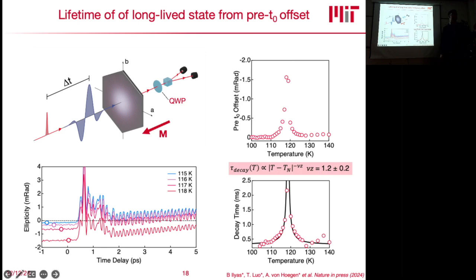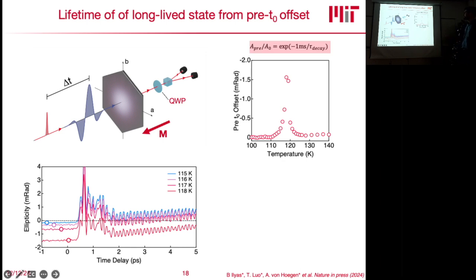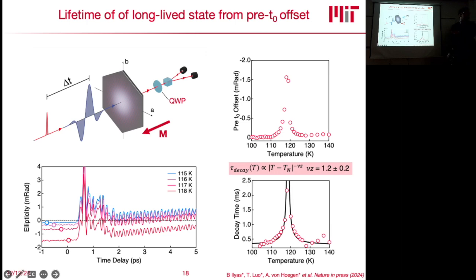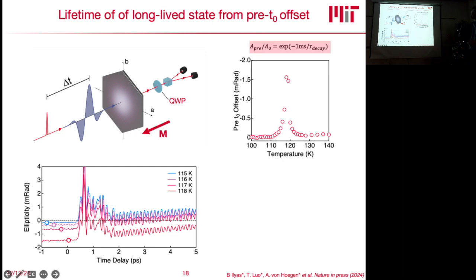Yeah, please. Can you really just move it up, because the signal is not just a constant shift. There's ringing. Yes, so you cannot necessarily just move it up. You would need to work out these things. This is also a very simplified expression, because this pre-time zero signal is the cumulative effect of multiple laser pulses. For this reconstruction, we took this into account. I'm just stating this equation to make it simpler. But it is actually a cumulative effect, since it lives for 2.5 milliseconds. It's not only the next pulse, but also the one pulse over.